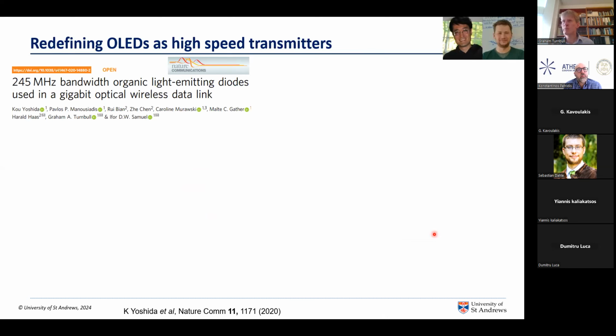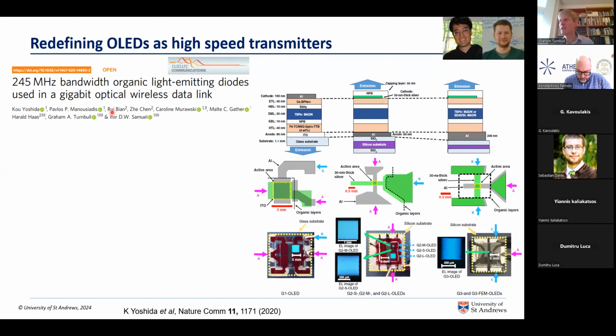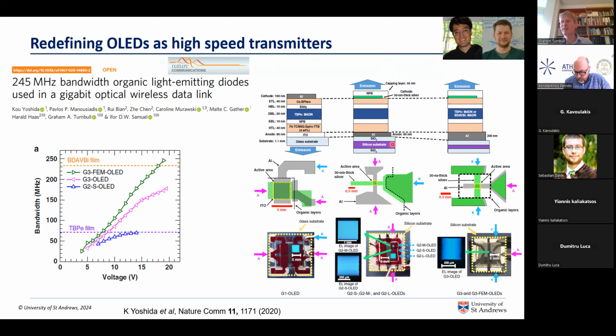Kou Yoshida and Pavlos Manousiadis spent some time trying to engineer very fast organic LEDs for a different application. We've also been interested in using OLEDs as Li-Fi sources, for very fast optical wireless data transmission. To do that, you need to be able to modulate your OLED on and off very fast. So Kou spent a lot of time engineering the organic LED, with the organic layers between a metal contact and a transparent contact, to minimize RC time constants, maximize the speed of light emission, and maximize the speed at which charges travel through the device. In doing so, he was able to modulate devices on and off at hundreds of megahertz.